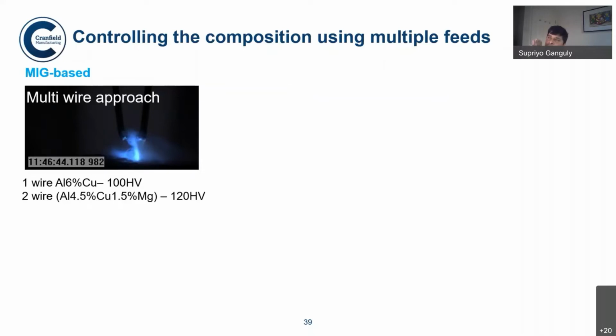And there's a huge solidification range which results in that. So this multi-wire approach was actually done in order to get rid of the large solidification range, or rather, in other words, to modify the solidification path in a manner that the solidification range becomes very small, and therefore to avoid solidification cracking.